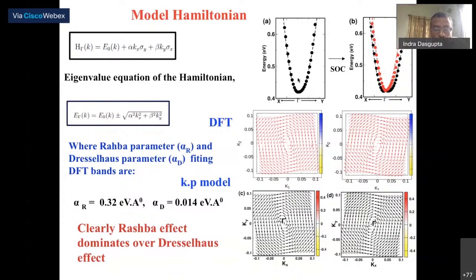Once you have this model at your disposal, you can go ahead and calculate your Rashba coefficient and Dresselhaus coefficient. We find for this system that the Rashba coefficient dominates the Dresselhaus coefficient. As a consequence, you have a typical spin texture of the Rashba kind.